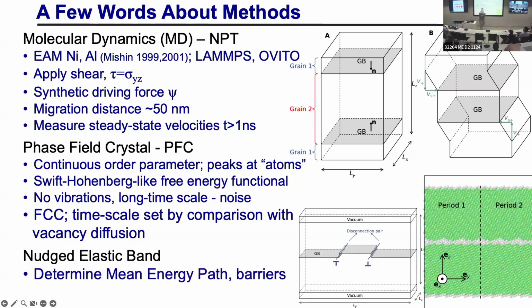Okay. And the third method we're going to use is nudged elastic band. You know what that is? Okay, good, so I don't spend too long on this. The idea is that we want to find the transition state, the barriers for the motion of a grain boundary. It turns out that the way grain boundaries move is by forming a pair of what we call disconnections, which have step character. So these are steps. If this pair of steps migrates outward, the boundary moves up.